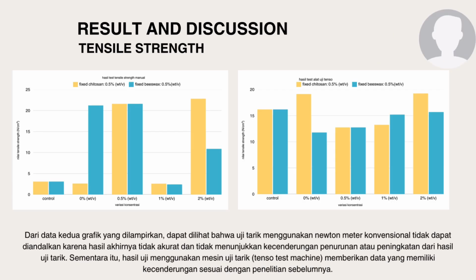From the data of the two attached graphs, it can be seen that the tensile test using a conventional Newton meter is not reliable because the final result is not accurate, as it does not give a tendency to decrease or increase from the tensile test results. While the test result using a tensile test machine gives data that has a tendency consistent with the previous research.